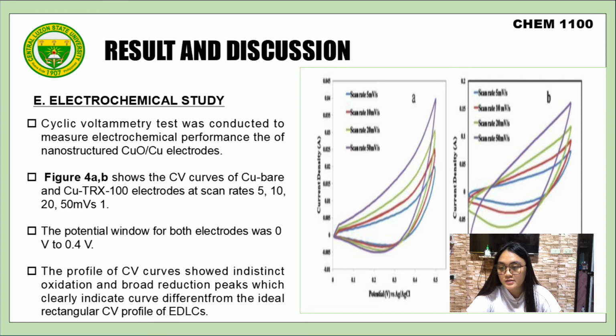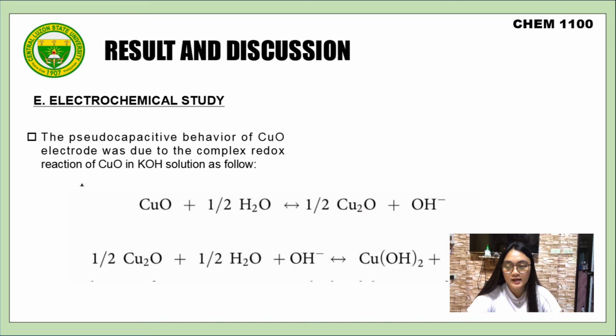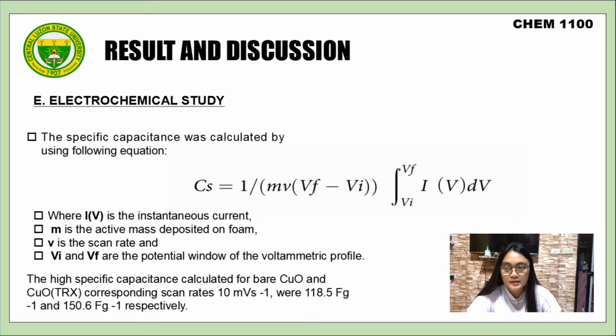The profile of the CV curve showed indistinct oxidation and broad reduction peaks, which clearly indicate a curve different from the ideal rectangular CV profile of EDLCs. Next slide, please. The pseudocapacitive behavior of the copper oxide electrode was due to the complex redox reaction of copper oxide in potassium hydroxide solution as follows. Next slide, please.